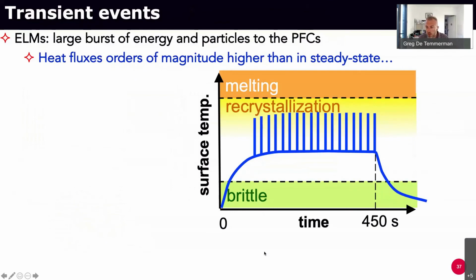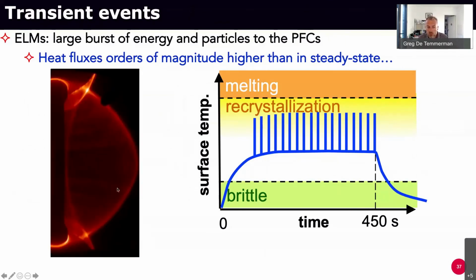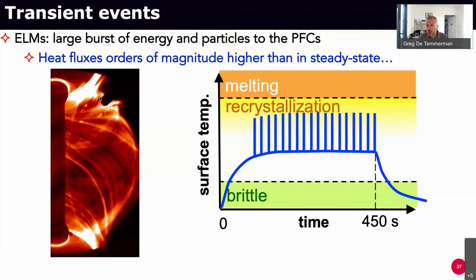And then the last thing I will touch upon is these issues of instabilities. Typically, a plasma would be really nicely confined, but then sometimes what will happen is something like that. So if you have seen pictures of the sun with those big filaments falling around or just being expelled, well, on the sun, this is really slow, it takes a large amount of time. Well, we have the same thing, but like fast forward. So those things are happening at 10 times, 100 times per second. Every time they expel a few percent of the energy of the plasma in a millisecond.